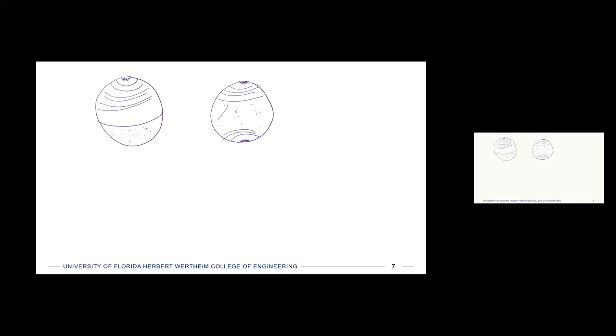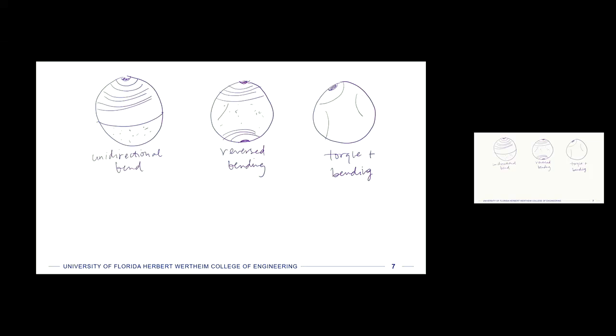right? Or now you can add in shear stresses, right? So this would be unidirectional bending, reversed bending, or if there's a high torque component, you can have torque plus bending. And that's where you get things growing a little bit in a weird way, right? So if it starts here, then it might actually come out and propagate around the edges more, right? And then the beach marks might happen in sort of some different geometry, because we know from thinking about shear stresses that the maximum is always at the periphery, right? So if the maximum shear stresses are at the periphery, then the crack will propagate sort of where those maximum stresses are around the periphery before it extends to the center.